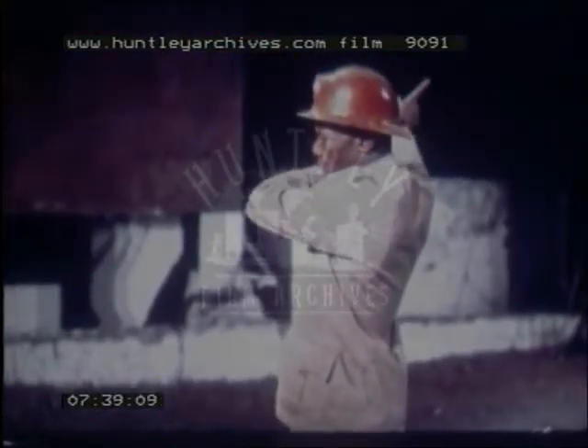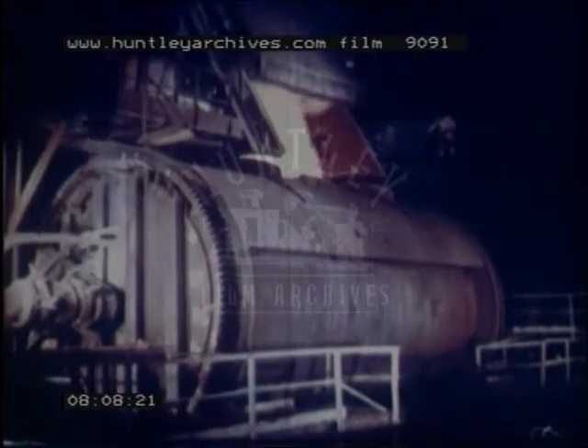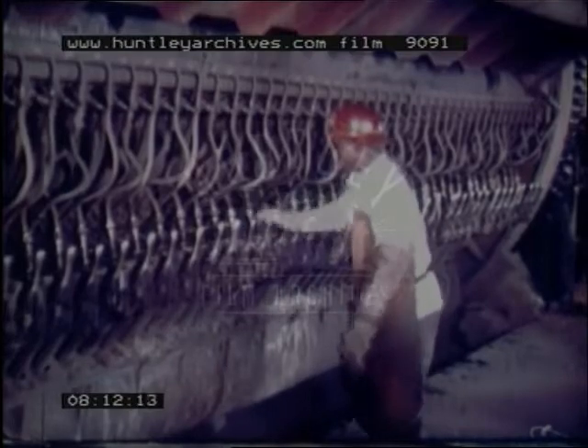It is then transported by a loading bridge at the same height as the converter, an enormous cylinder about 30 feet long and 15 feet in diameter. The conversion process lasts from 3 to 4 hours. This operation converts the metallic sulfides into copper by a final elimination of sulfur and other impurities, mainly iron. Compressed air is blown into the liquid matte through 50 tuyères and transforms the sulfur into sulfurous anhydride, which is exhausted through a tall chimney stack.